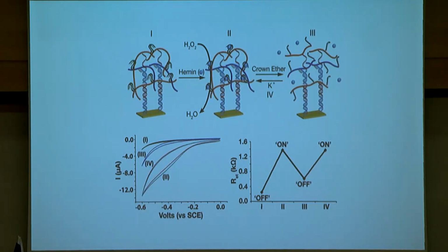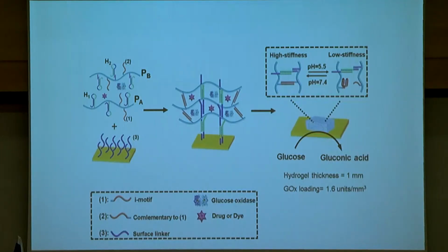You can incorporate into this G quadruplex the hemin catalyst, and then we can switch on and off the electrocatalytic properties of this electrode, for example, towards the reduction of hydrogen peroxide. So this is a very simple example of trying to make a smart hydrogel surface on the electrode. And from here I will move to a slightly more difficult and more complex system where we try to make this artificial pancreas. And the way to do it is exemplified here.